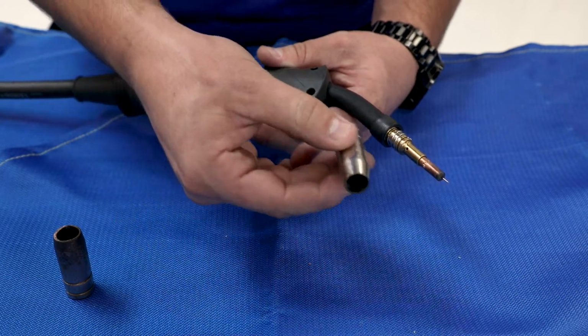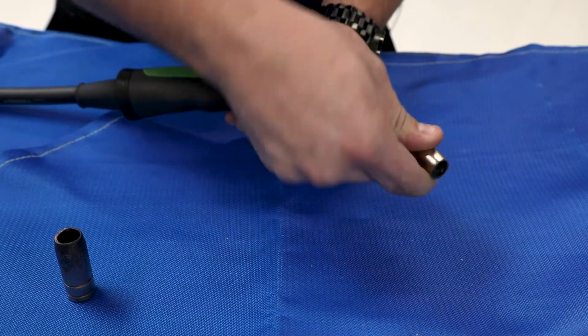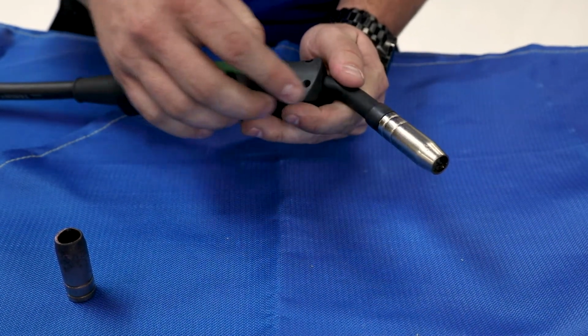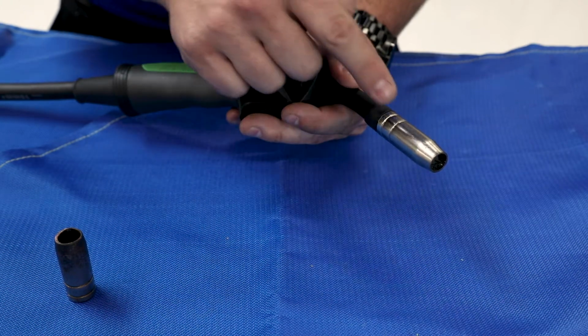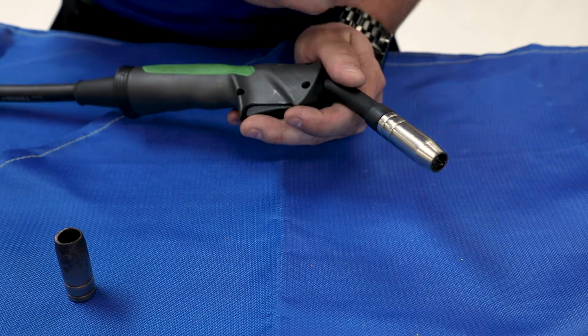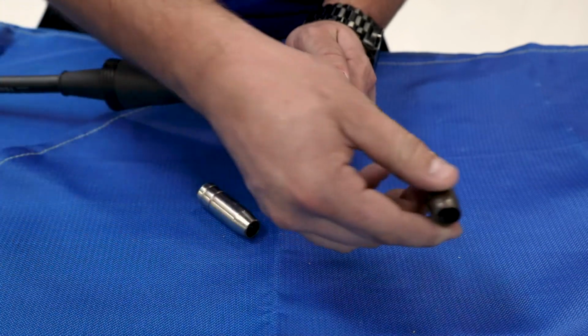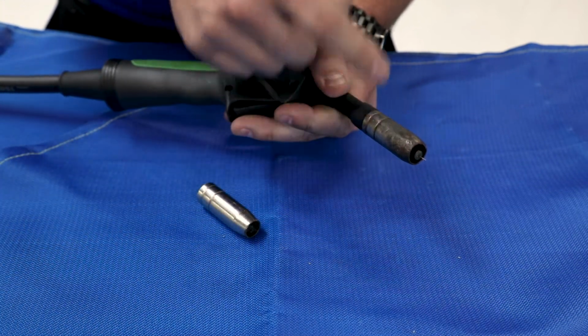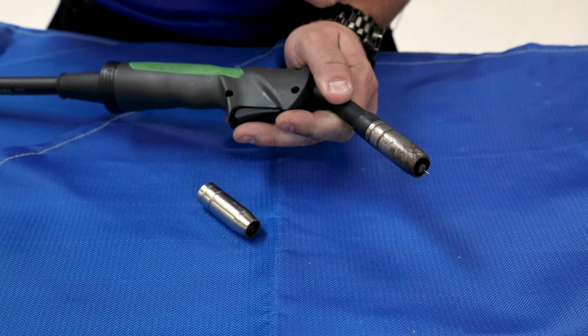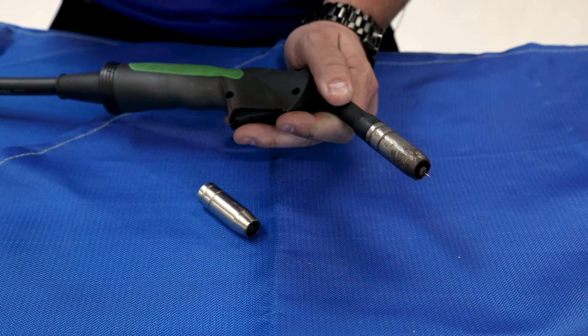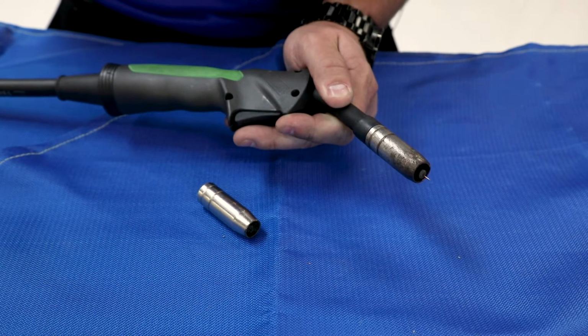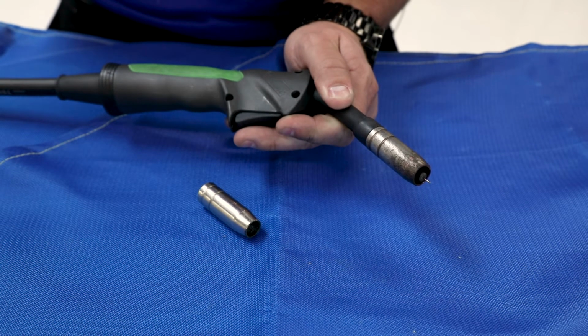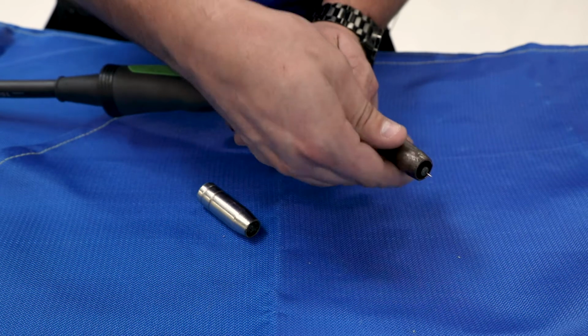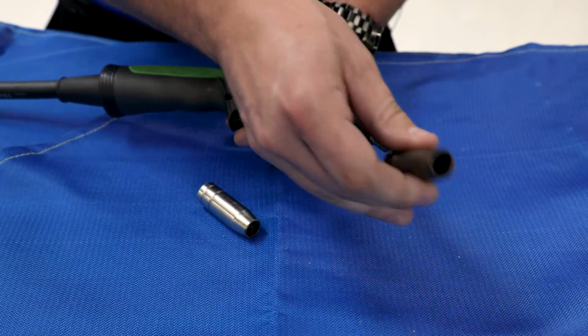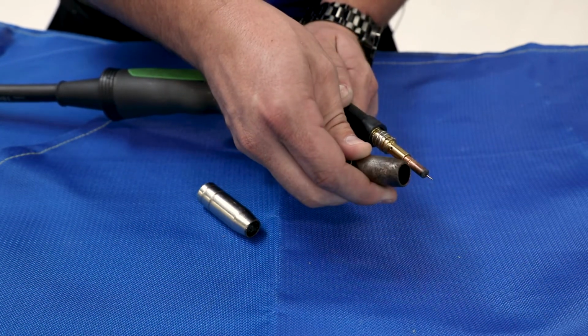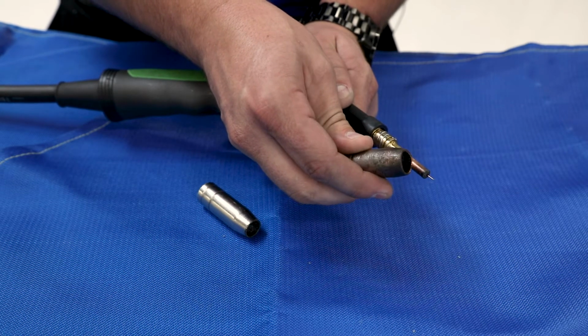When we're looking at the gas shielding nozzle, we want to make sure that we have a good gap between the contact tip and the top of the shielding nozzle. If we have a gas shielding nozzle that does not have a good gap, such as this one, where the contact tip actually sticks out of the nozzle, that's going to cause the gas to be dispersed across the panel instead of into the weld bead. This will cause porosity inside of the weld bead. So we want to make sure that the gas nozzle is in good shape and we don't have inconsistencies along the top of the nozzle itself.